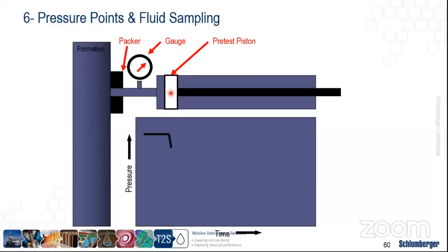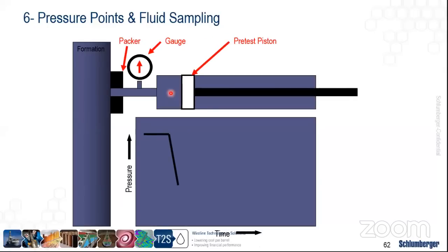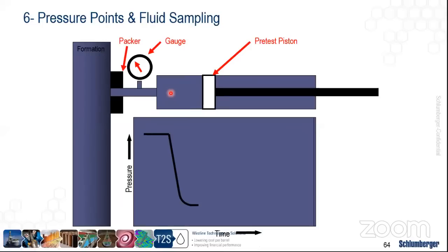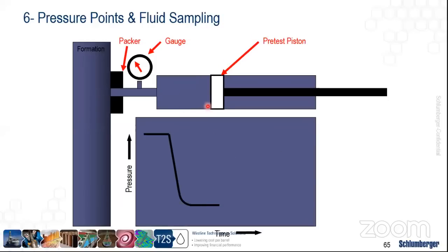So once we have the piston at position 0, for example, then we start to create a drawdown. We start to move the piston inside the tool in order to create a negative pressure. So negative pressure starts to build up at this vacuum. Once we reach a certain position, we go to what we call the drawdown limit. This drawdown limit is the point where we stop the piston itself and wait for anything from the formation to come inside the piston or the vacuum itself.